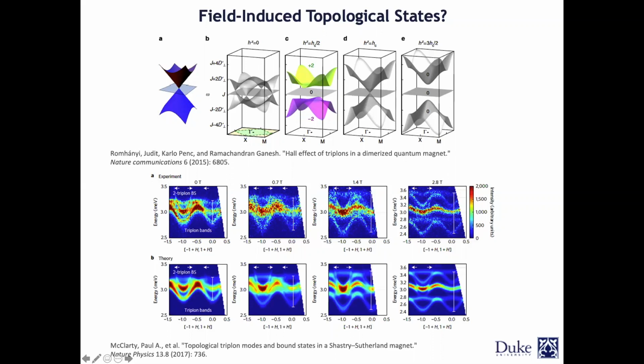So this is what was originally discussed in this paper, which is a theory paper, and later on a very high resolution neutron experiment was done. It was not very successful in convincing everyone about this fact, but at least it opened the door that this type of experiment can actually be done with neutron scattering and can be probed. They said that at around 1.4 Tesla, there's going to be a Dirac cone, or a touching. That paper was published in Nature Physics.